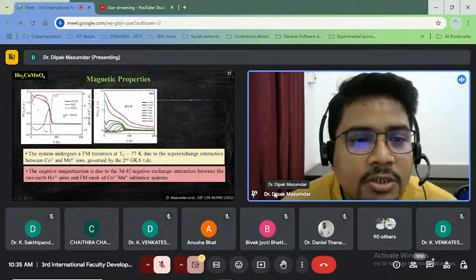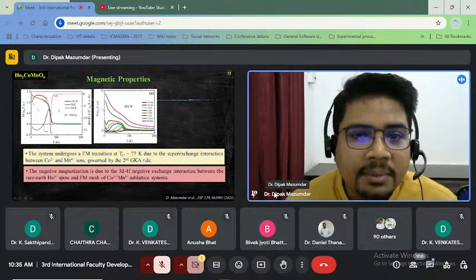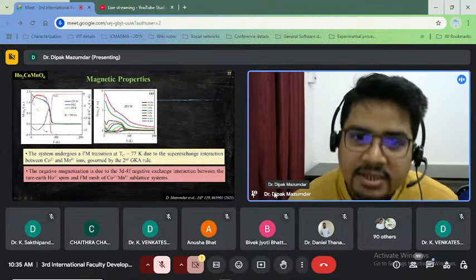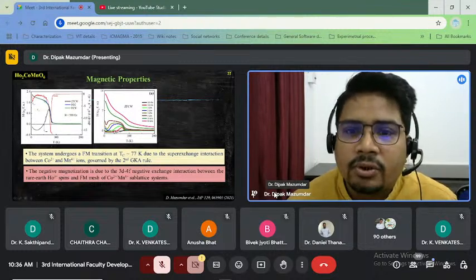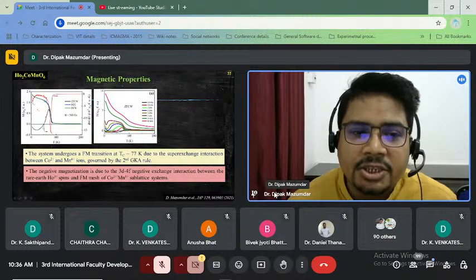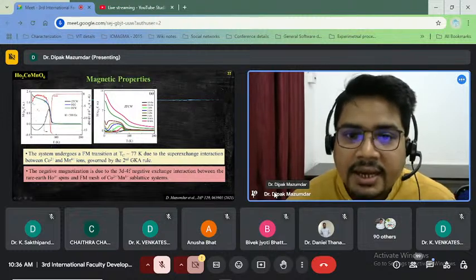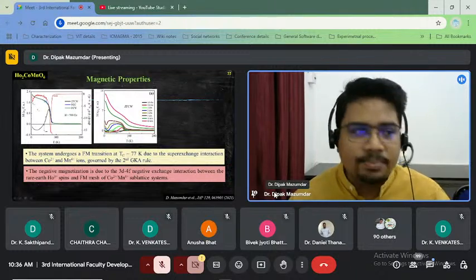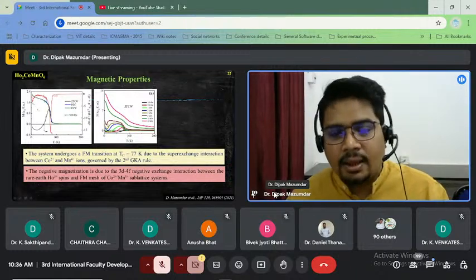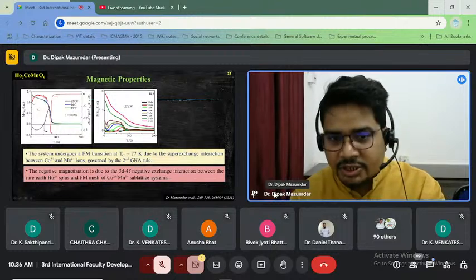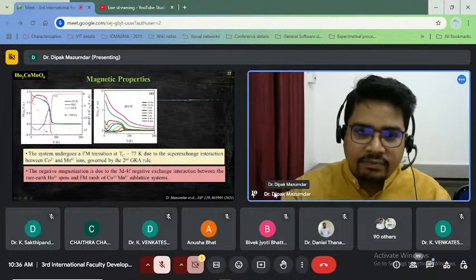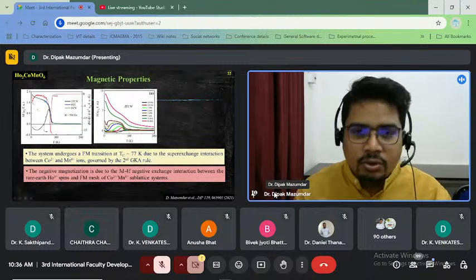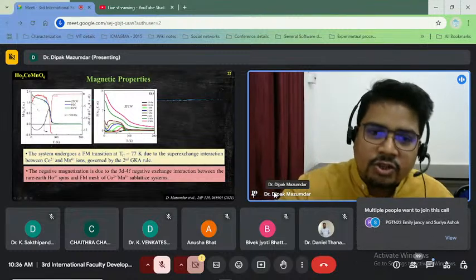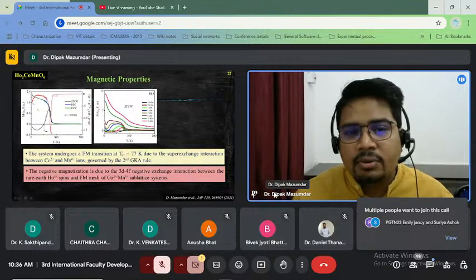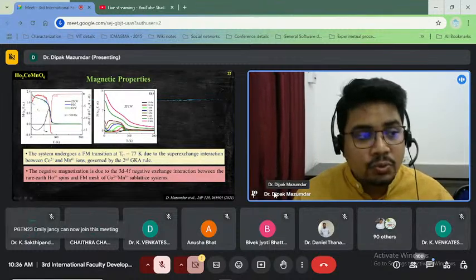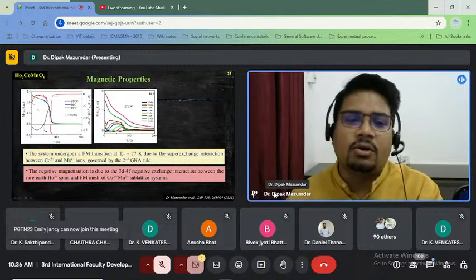Then, after this small field, we checked the magnetic behavior for various magnetic fields, and we can see that above 1 kilo-oersted magnetic field, the negative magnetization behavior disappears. This is due to the application of the magnetic field, which tends to align the magnetic sublattices along the field direction. As a result, this negative exchange interaction is weakened and our magnetization increases. And you can see there is an upturn. This upturn is due to the start of ordering of holmium ions.